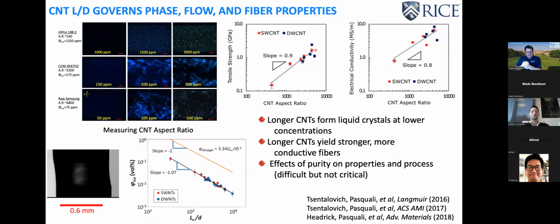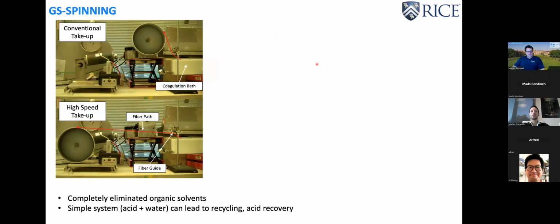This also affects your phase behavior, and we found ways to use phase behavior and also rheology to measure, for example, aspect ratio. So what this has given us is the target. How do we measure whether the material is good, how good it is, what are the potentials? Now, another effort that we've had is to make fiber spinning more efficient. This is how we used to make fibers. Look how slowly this roller is moving. And now this is what we can do. So we sped up the process dramatically.